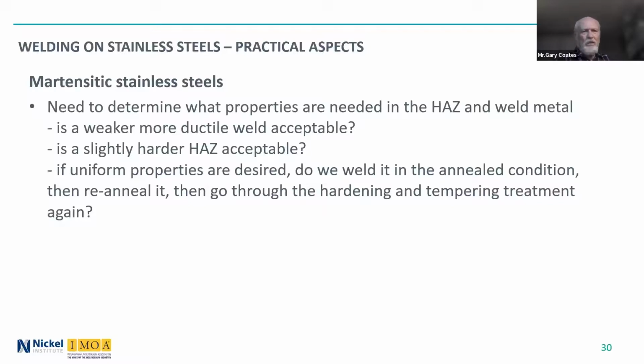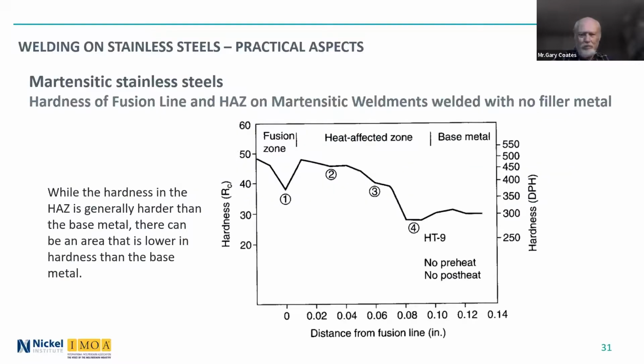than the base material? And if you really want uniform properties, well, the one way to do it is to weld it in the annealed condition, re-anneal it, then go through a hardening and tempering treatment again. All that adds cost and difficulty to welding them. So these are particularly tricky alloys to weld.